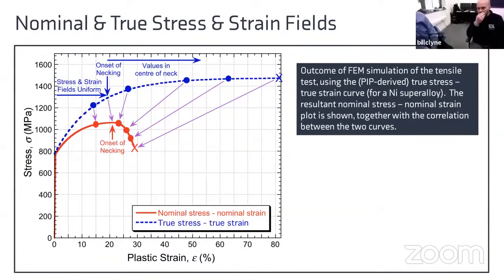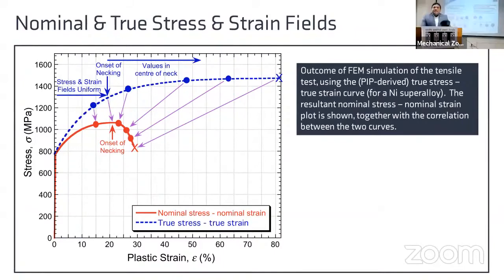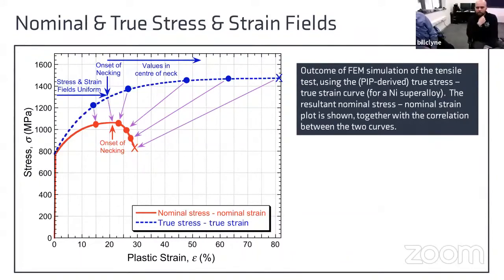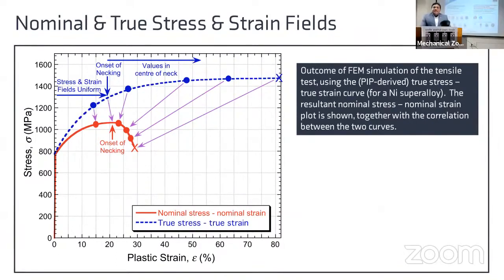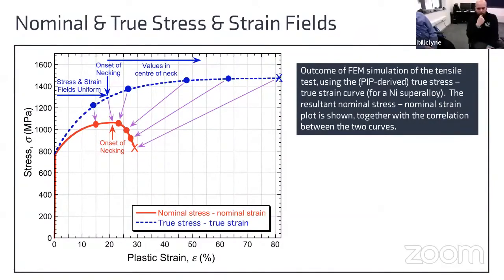Yeah. The answer to that is that it doesn't need to be highly polished or anything. One of the big advantages of doing this on a relatively coarse scale is that it's not very sensitive to surface roughness. Of course, if it's very rough, if you have a thick oxide layer on the surface, or very deep grooves, then it might create an error. But generally speaking, you just need to grind this to a reasonable finish. You don't even need to polish it, and if you do, you certainly don't need to polish it very finely. We typically recommend that a grind of P1200 grit is appropriate. That's more than enough. So we don't suffer, like Bill said, the problems that you might associate with nano indentation, where you do need a very good finish to make sure that it's not going to affect the response of the material, because you're indenting on such a fine scale. So the requirements for surface finish are actually not too demanding.